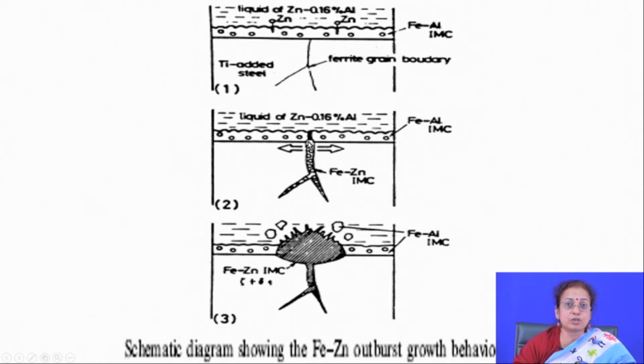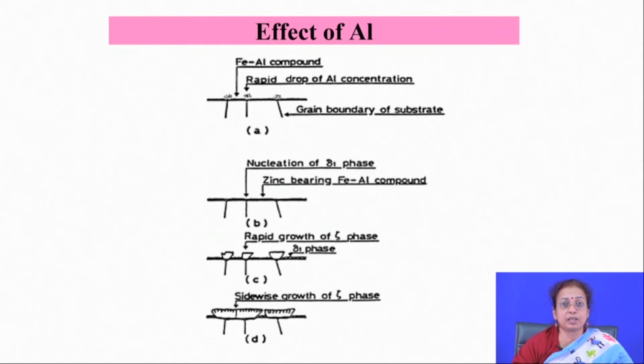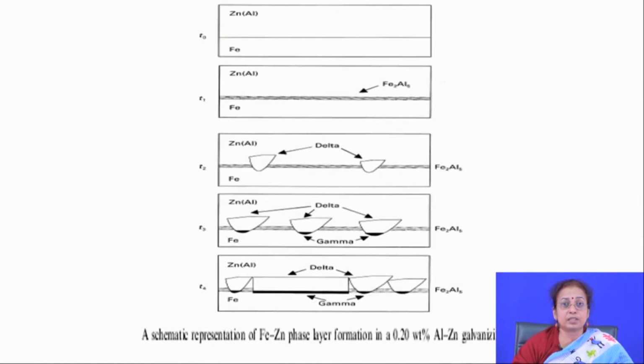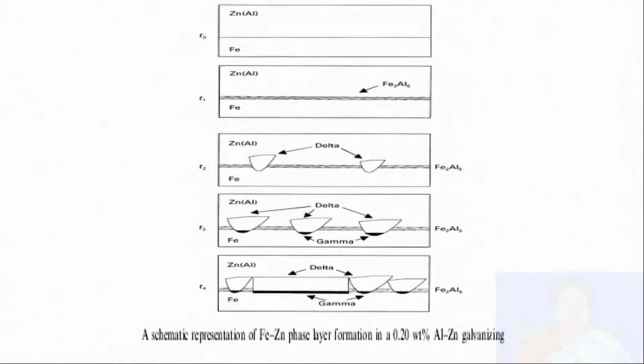So, when you just go on taking it out, you will find that the zinc coating basically falls out. So, you have to be very careful and control the time carefully, so that there is no chance of outburst formation. Otherwise, you apply some more aluminum in the coated layer, so that there is no possibility of outburst formation at the surface.